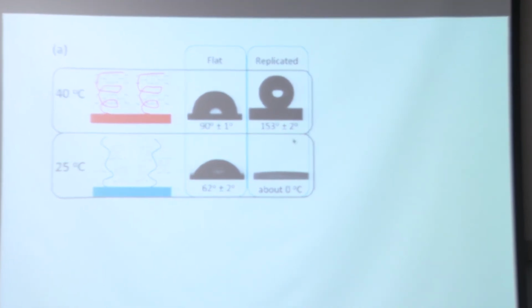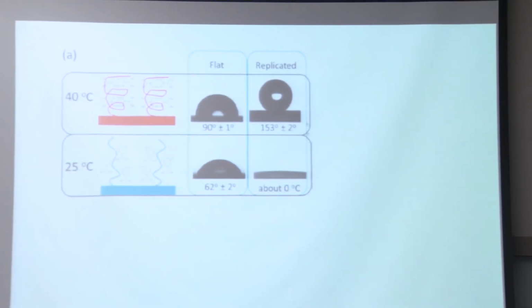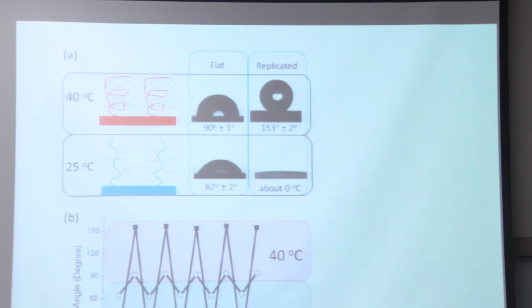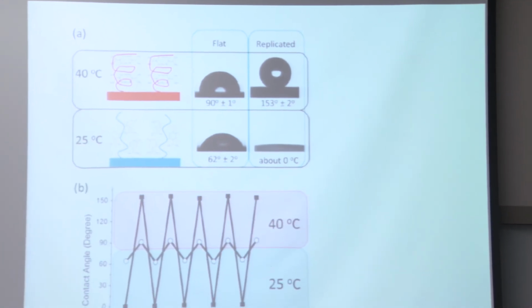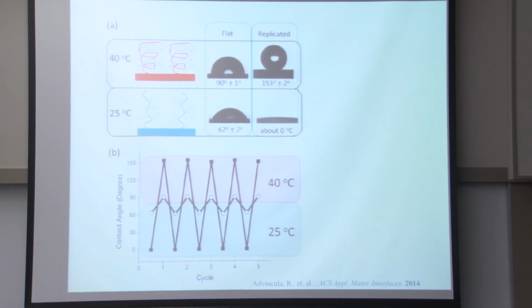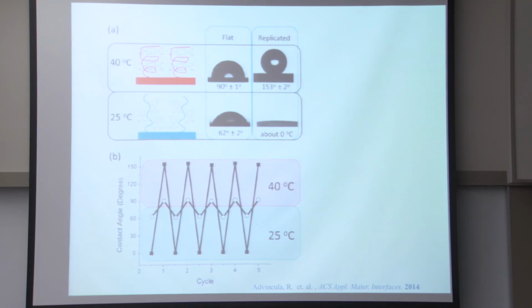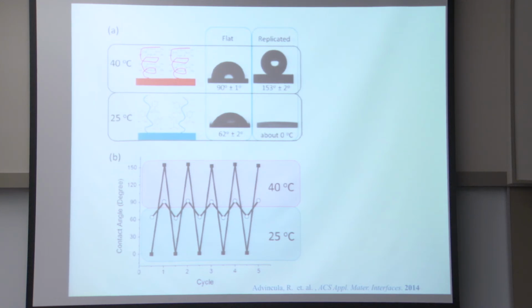However, by using a lotus leaf-like surface, you get a very high wetting change—from 0, superhydrophilic, to 153, superhydrophobic—based on just a 15 degree Celsius change. And we can do this back and forth. This cyclical behavior was afforded by that very thin film of the polymer brush of polyNIPAM combined with the lotus leaf-like structure.